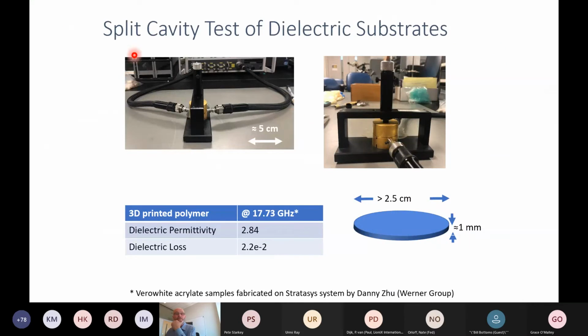And then split cavity. In this case, I did show that example with the aluminum oxide. Here we have something that's about 1 millimeter thick, a couple of centimeters in diameter, and we put that sample right in the middle of this cavity here, and we can get these sorts of values at one frequency. Where I showed the parallel plate method, where we can go like 9 orders of magnitude or whatever in frequency, here we do a lot of work and we get one frequency measured at about 17 gigahertz.